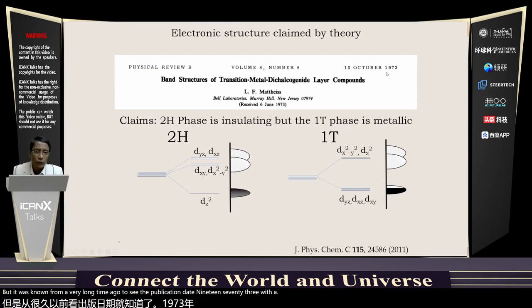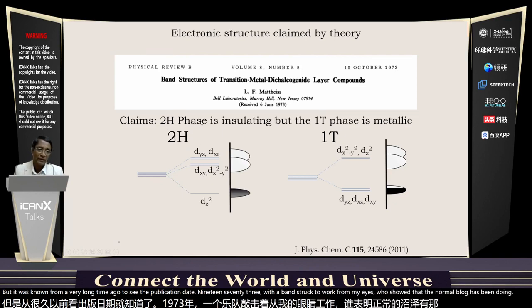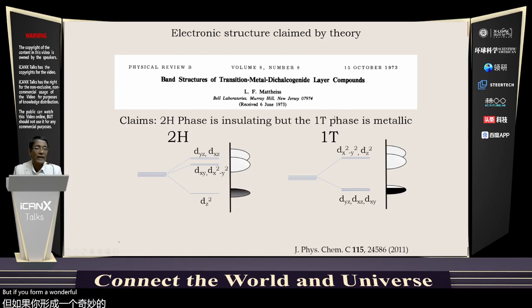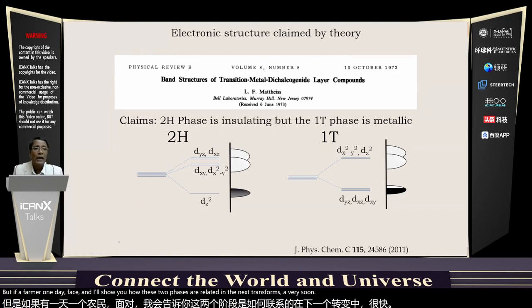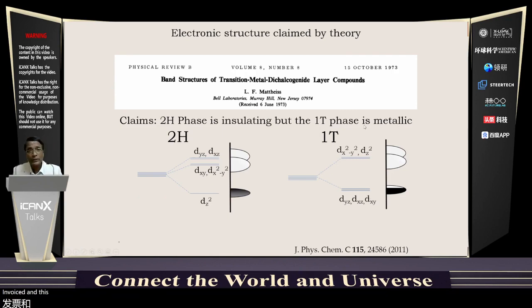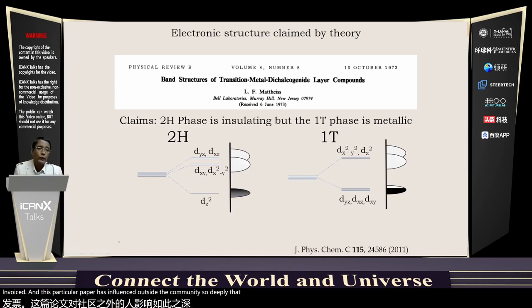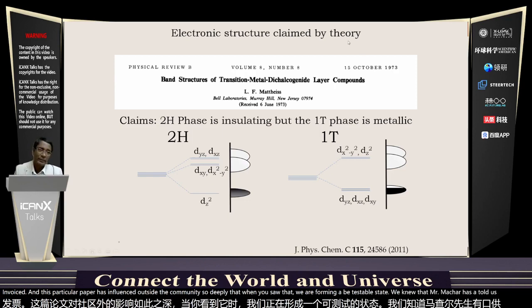There's a band structure work from Mattheiss, who showed that the normal bulk has a 2H phase. It has a wide band gap insulator from band structure calculation. But if you form a 1T phase, and I'll show you how these two phases are related in the next transparency very soon, that forms a metallic MoS2. And this particular paper has influenced the community so deeply that when you saw that we are forming a metastable state, we knew that Mr. Mattheiss had told us that the metastable state is the T phase, and the T phase is metallic.